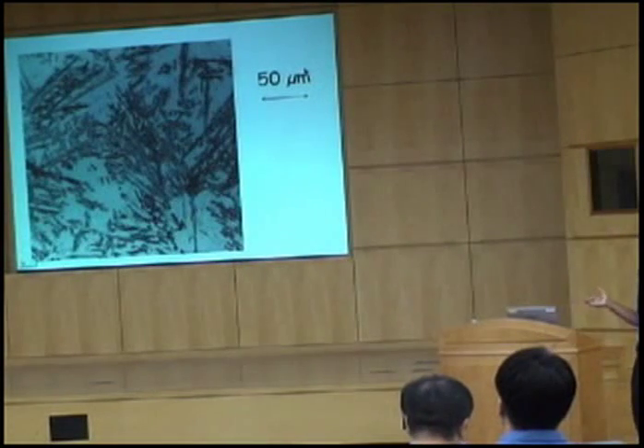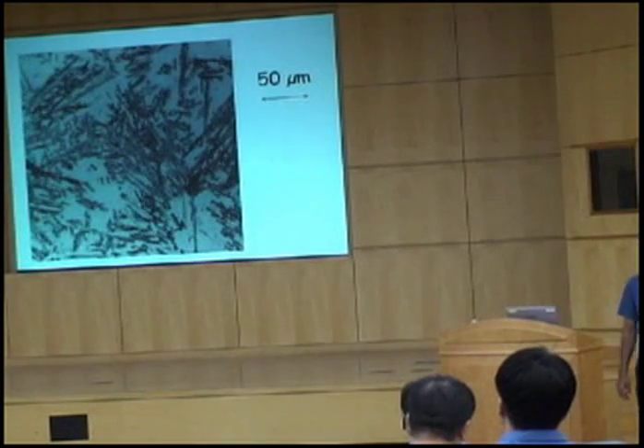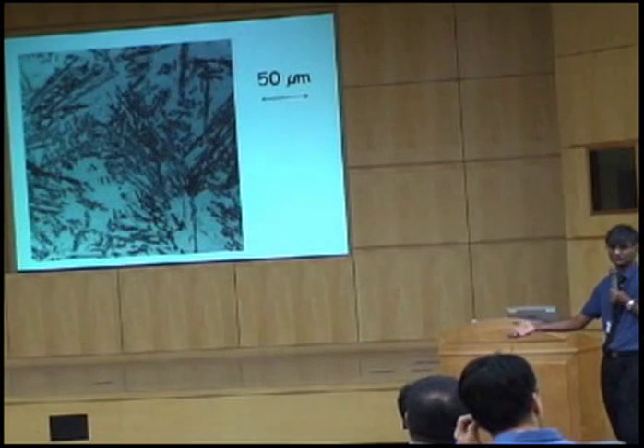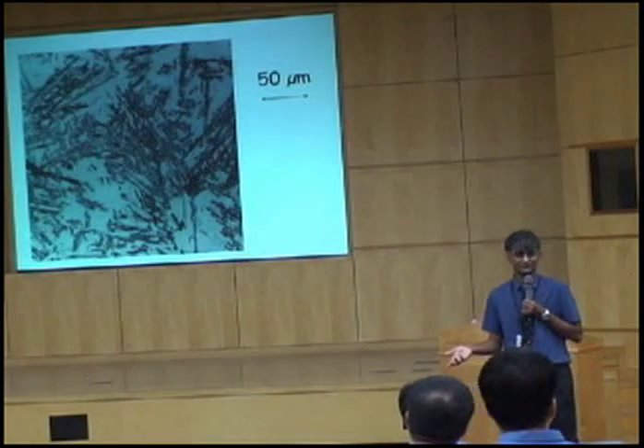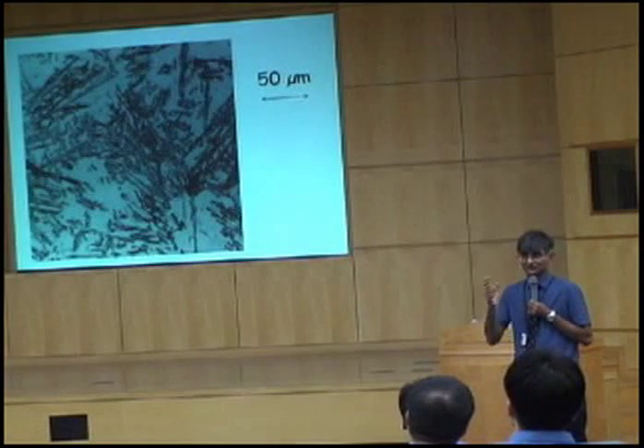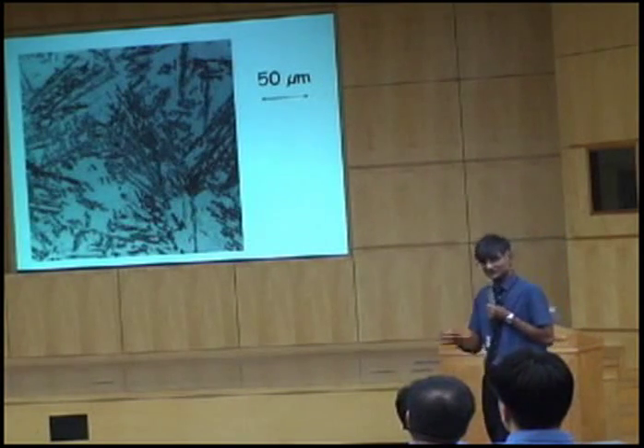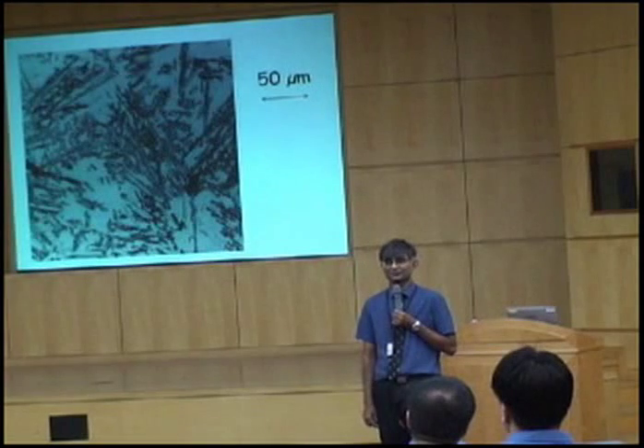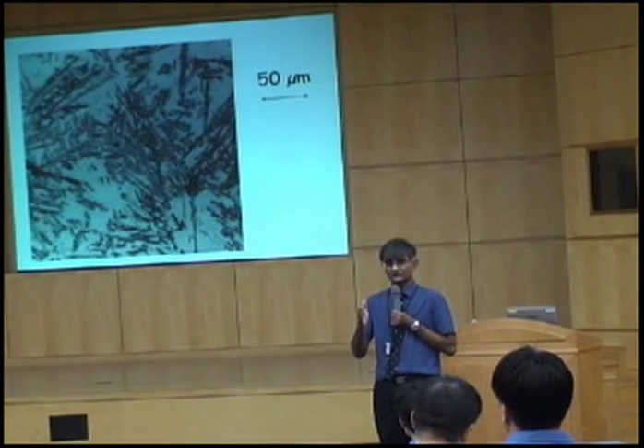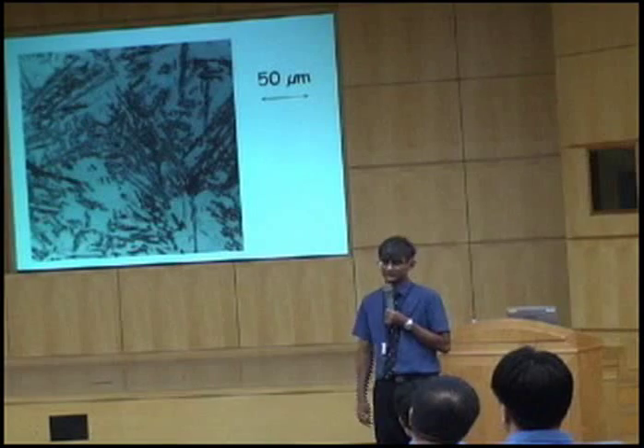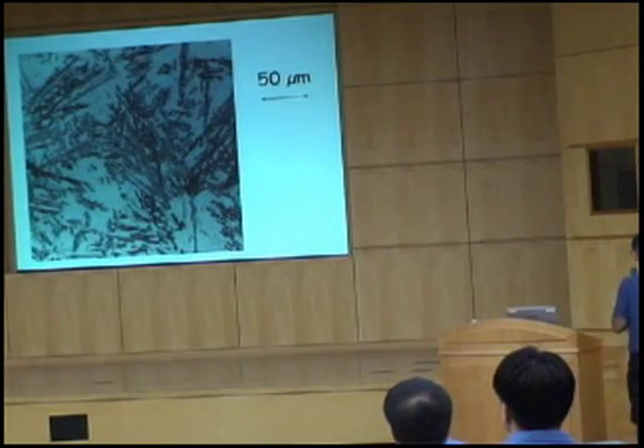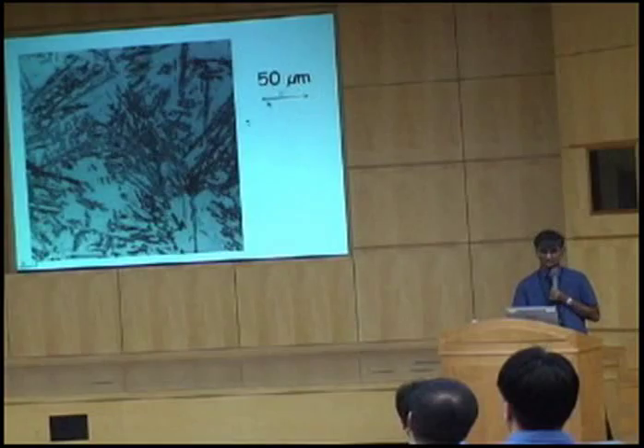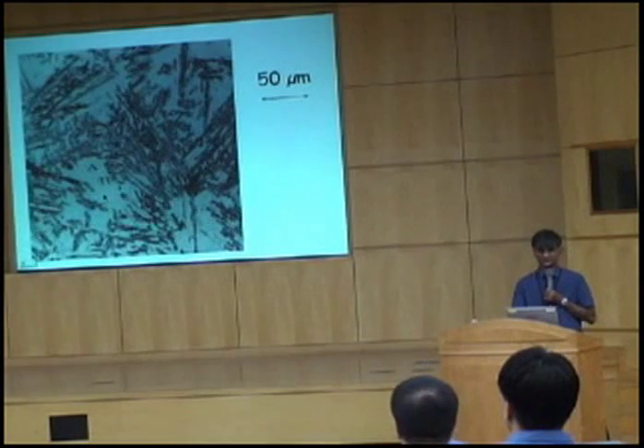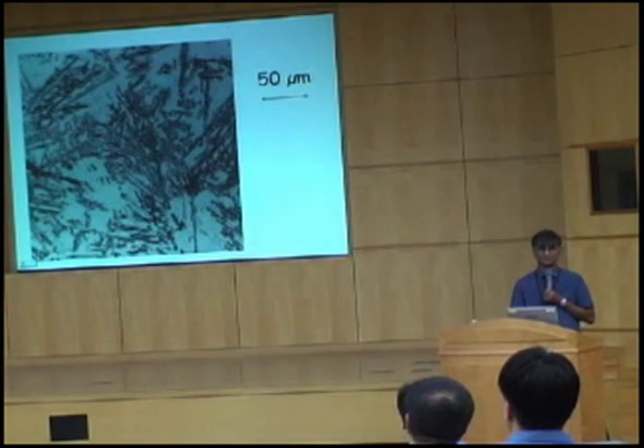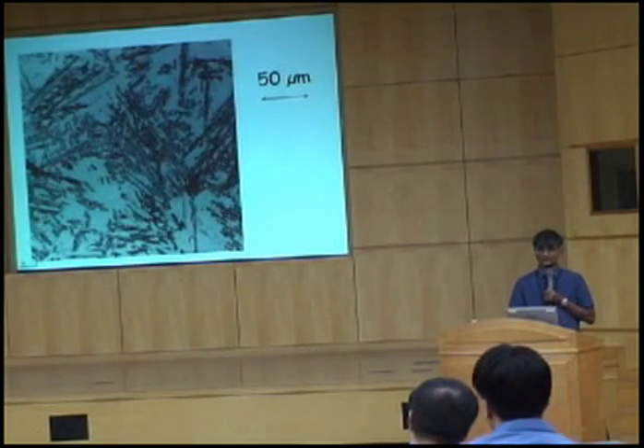Okay? Now, how can we get rid of these large regions of austenite? Well, if we allow more bainite to form, then you can get rid of those regions, right? But there's a problem. And that problem is the T0 curve that I explained to you yesterday. That T0 curve stops the reaction from going further. So here, even if I hold this material in the bainite transformation range for several years, this will not change. Because that T0 curve we discussed yesterday stops more bainite from forming.